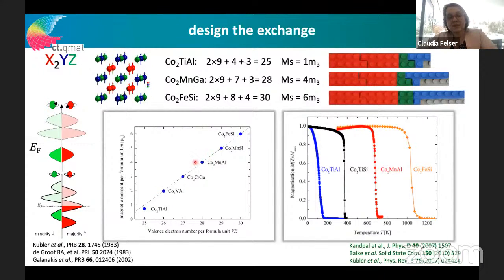And you can read this even here on this graph. We have 28 valence electrons and the formula for saturation magnetization, and these are experimental data of many of the cobalt Heusler compounds. They are all lying on this half metallic line, and there's nice work done in Mainz on cobalt manganese silicon, which shows some evidence in angle-resolved photoemission for half metallicity. At the same time, TC is quite high, which means the compound is ferromagnetic below this ferromagnetic to paramagnetic transition. So TC is very high, so these materials are really interesting.